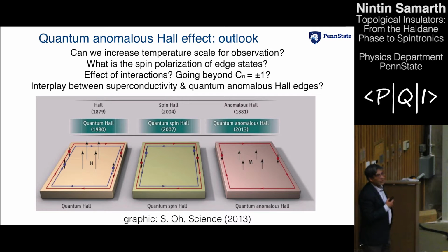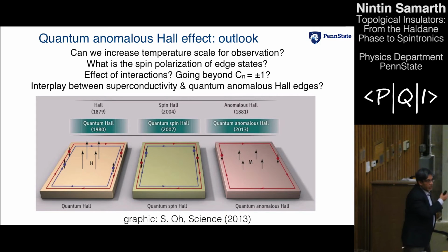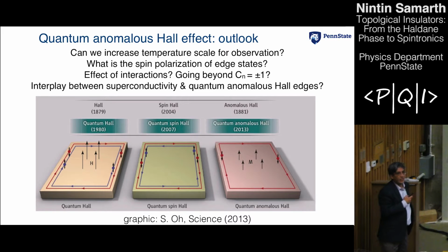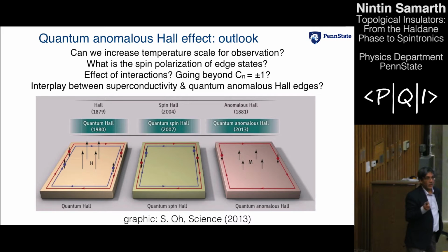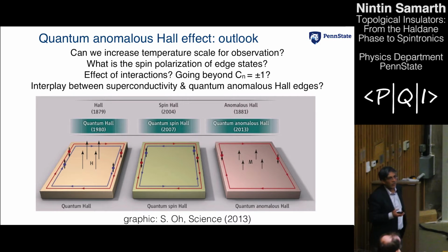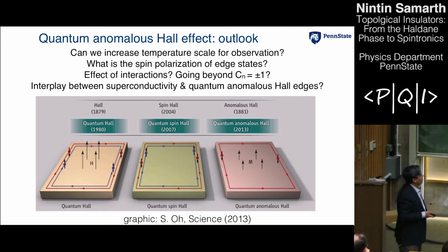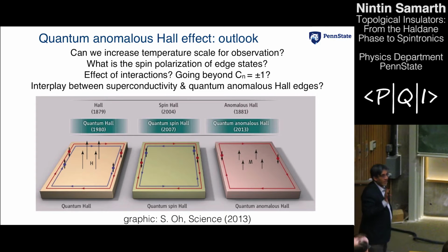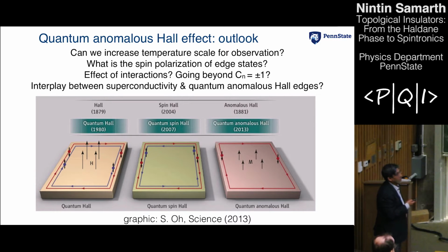Well, there are some important questions that arise. First of all, these measurements have been done at dilution fridge temperatures. So can we increase the temperature scale for the observation? There's a group in Japan, Tokura's group, that has recently demonstrated that they can actually see the effect up to about a few Kelvin. They've done this by using some materials magic that no one quite understands why it works, even though they have some speculation as to why it works, but they've been able to make samples like that. But can we take it much higher? It's not clear how we increase that temperature.